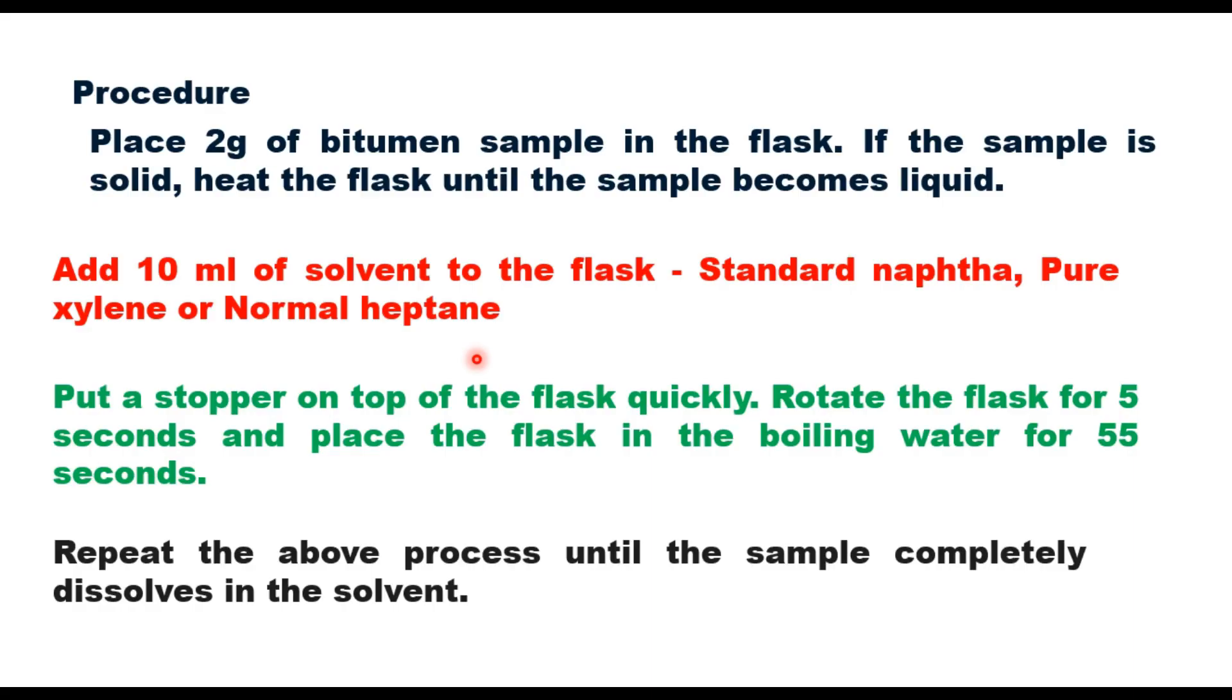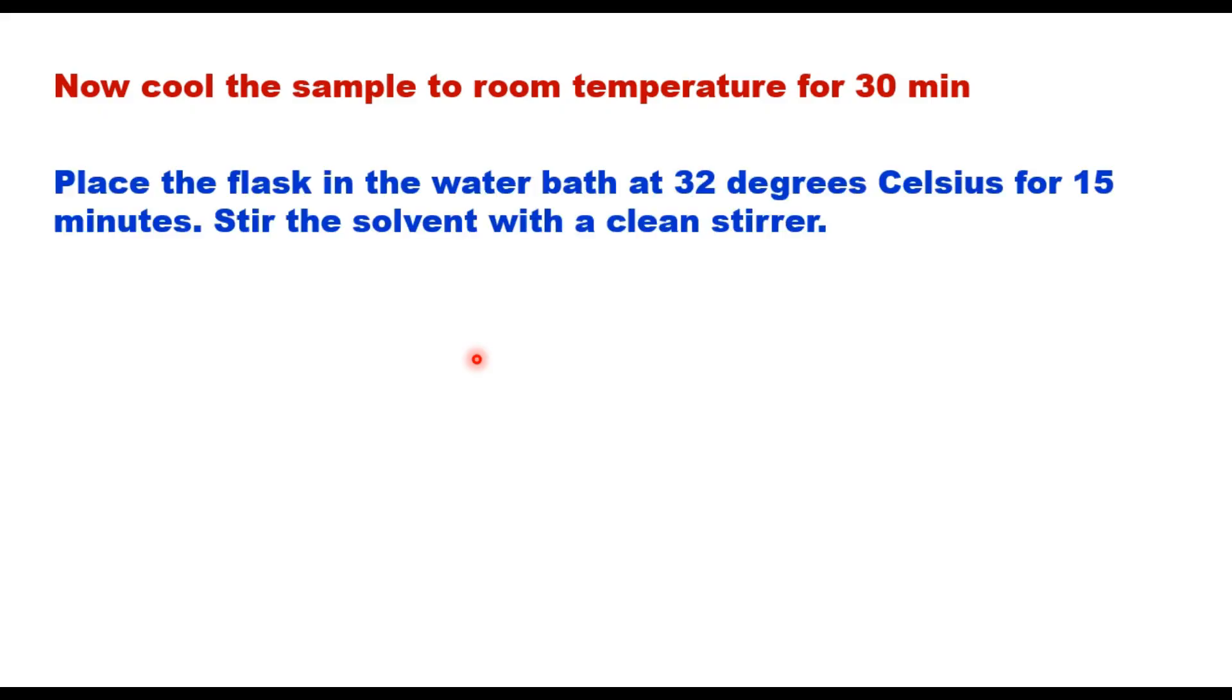Repeat the above process until the sample completely dissolves in the solvent. Now cool the sample to room temperature for 30 minutes, and then place the flask in the water bath at 32 degrees Celsius for 15 minutes.